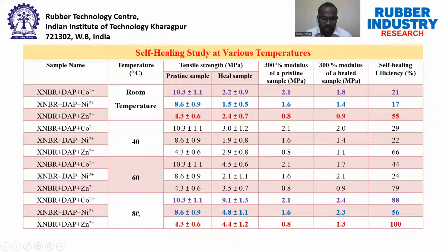At 80 degrees centigrade, after 24 hours, the cobalt modified compound has a healing efficiency of 88%, the nickel modified compound 56%, and the zinc modified compound 100%. So which means zinc can form more weak and dynamic metal coordination bonds compared to cobalt and nickel.